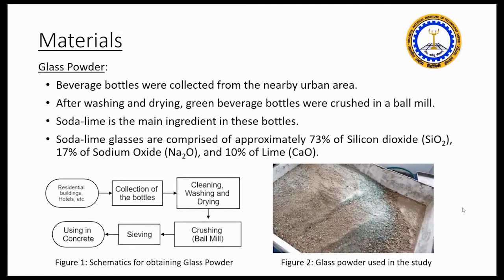We used beverage bottles which were collected from nearby urban areas. After washing and drying, green beverage bottles were crushed in a ball mill. Soda lime is the main ingredient of these bottles, and soda lime glasses comprise approximately 73% silicon dioxide, 17% sodium oxide, and 10% lime.